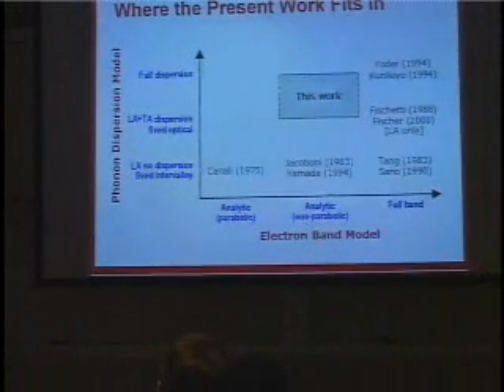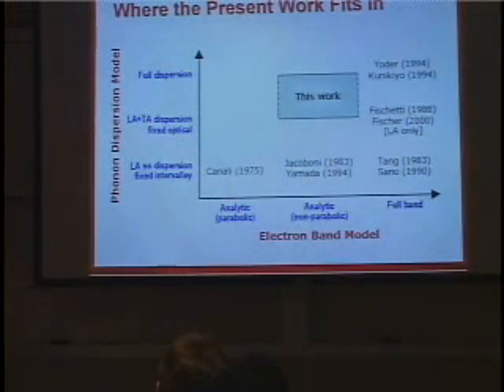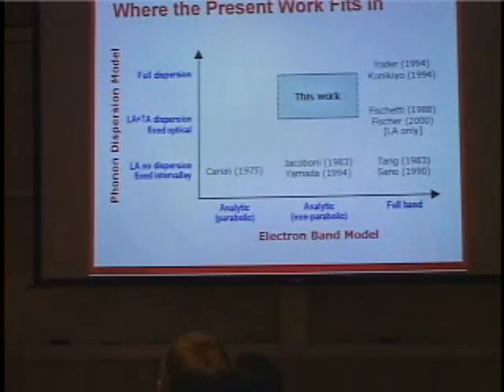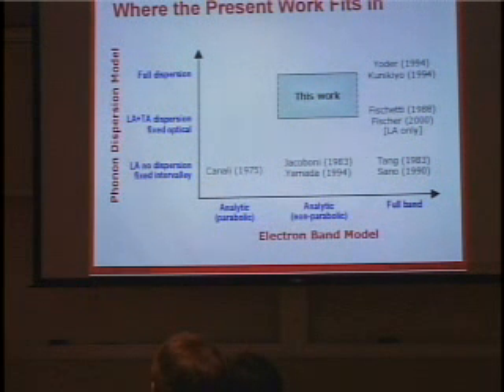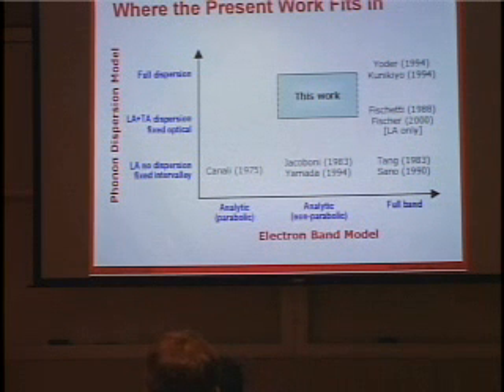The other dimension of this work is the phonon dispersion model. As far as phonon dispersion models in Monte Carlo, typically people have simply included longitudinal acoustic modes without any kind of dispersion, and they've assumed just fixed energies for the intervalley modes, for the optical modes, as we'll see. There's been some recent work which has taken into account both the longitudinal and transverse modes, but again assumed only fixed optical modes.